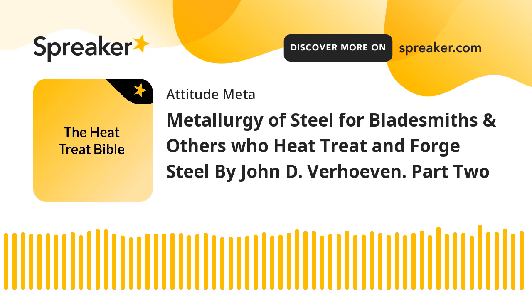To observe the true details of the microstructure, one must magnify a small region within a pearlite grain to a very high magnification, as shown on the lower right of Fig. 3.7. The structure consists of alternating plates of ferrite and cementite. The ferrite plates are much fatter than the cementite plates, occupying 90% of the volume compared to only 10% for the cementite. At the pearlite grain boundaries one observes an abrupt change in the orientation of the plates, as shown for a real sample in Fig. 3.8 — a transmission electron microscope picture at 11000× magnification. The CM plates are only 0.1 micrometers thick, too thin to be resolved on an optical microscope. Although CM is brittle, pearlite is not, due largely to the fine size of the CM plates.